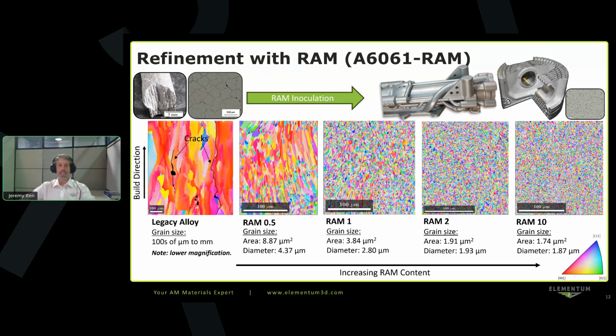So if you look, as you start adding these RAM reactive inoculants into the system, a RAM 1, for example, is a nominal 1 volume % of reactive product phase that's formed during the printing process. And you can see that's now a completely different microstructure. You can see the scale bar is also different than the legacy alloy because we're now looking much closer, because the grains are so much smaller already at nominal 1 volume % product phase.